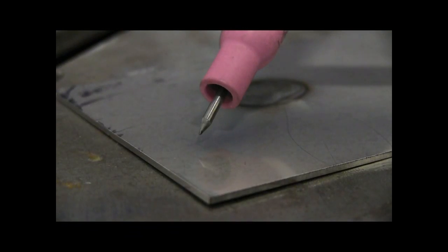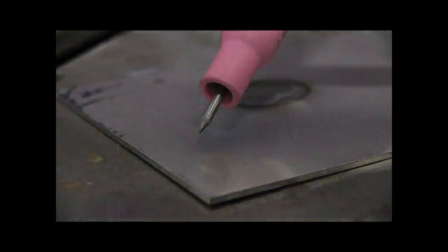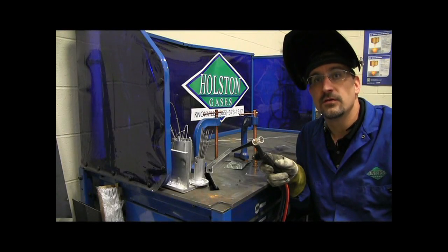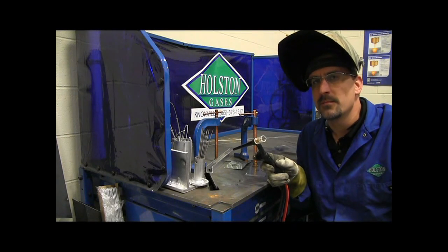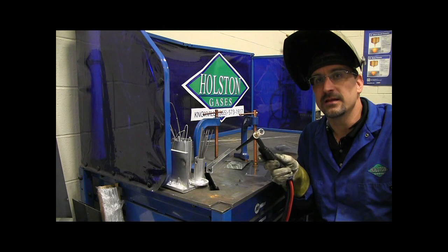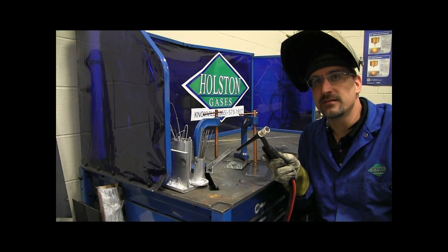And so you can see how the extreme point of the tungsten is oxidized and dull and gray. And while we were welding, it actually spit a little bit due to the inadequate shielding because of too small of a cup and too large of a tungsten stick out. And so now with the same flow rate, but a gas saver or a gas lens and the same tungsten stick out, we'll do the same test and we'll inspect and compare the tungstens.